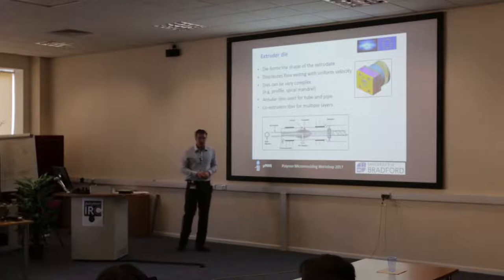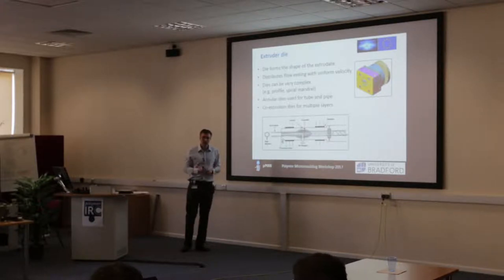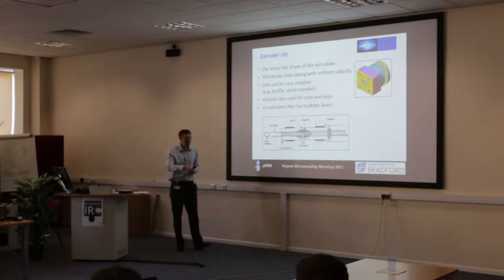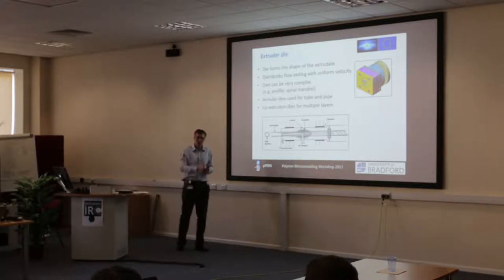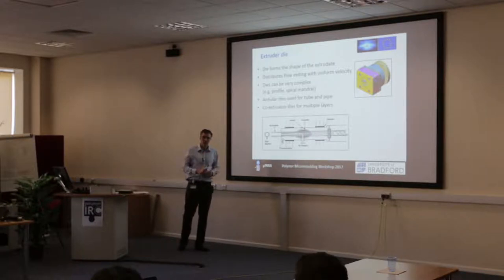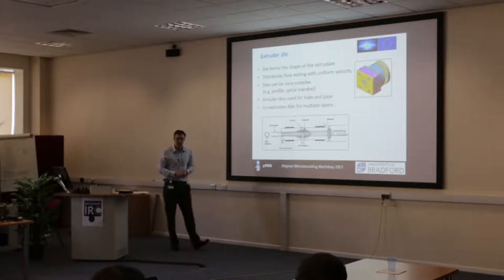There is in certain applications, but in single screw extrusion, the extrusion process runs completely full and it's under quite high pressure. So generally air bubbles aren't a problem. If we do have air bubbles entrained in the material, there are ways to vent. We can have a vacuum and put a vent port on the process, but that's more often done in twin screw extrusion, which is a mixing process, which I'll talk about in a minute.